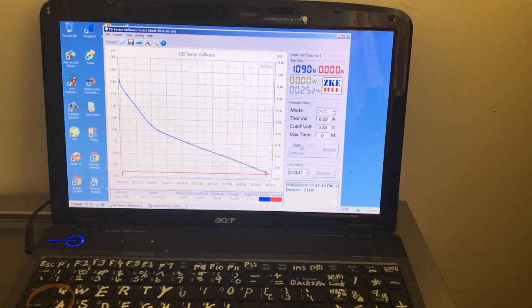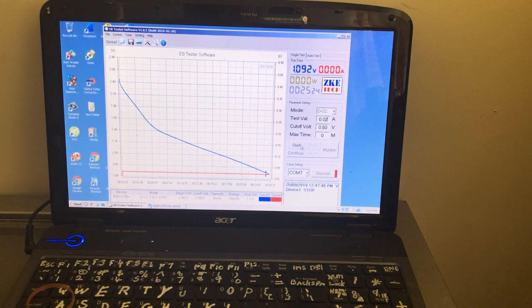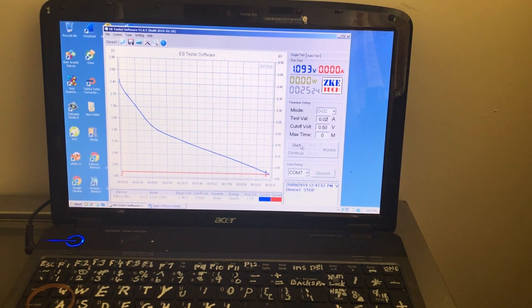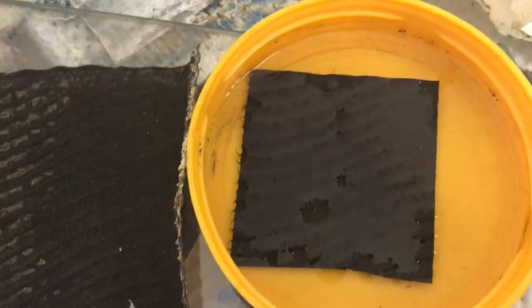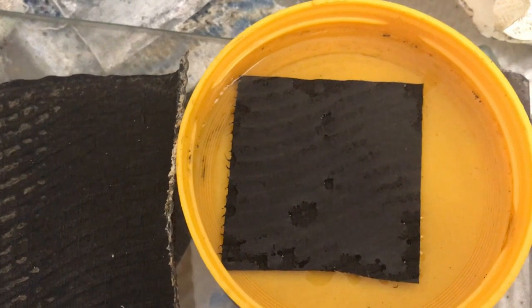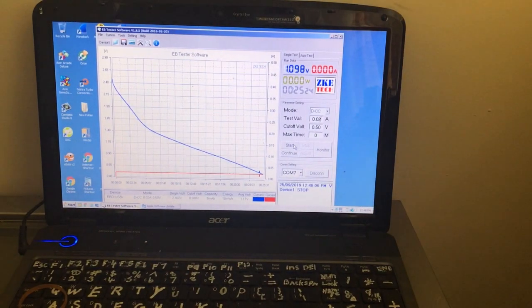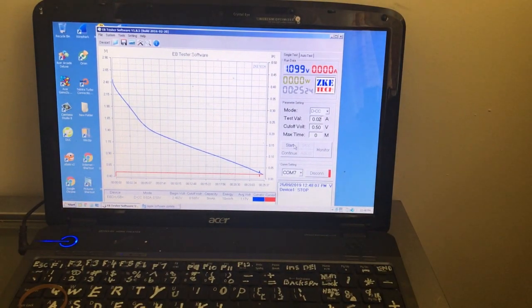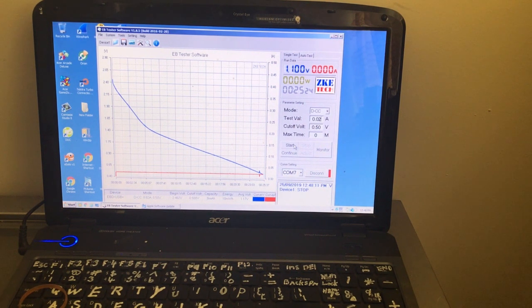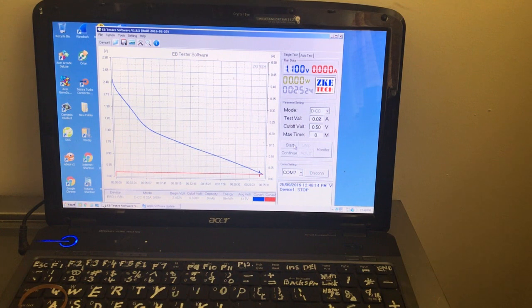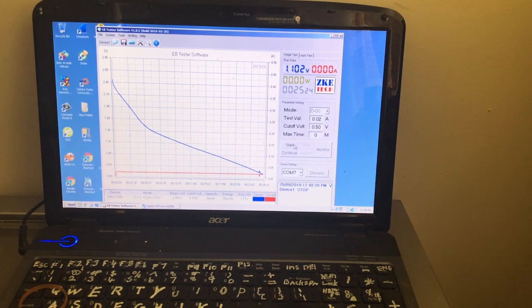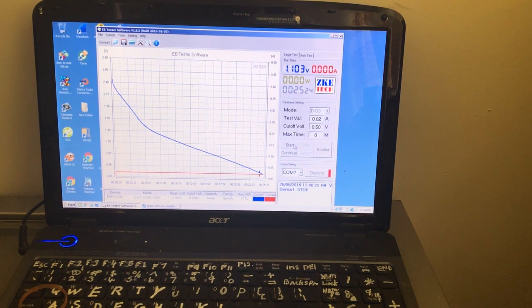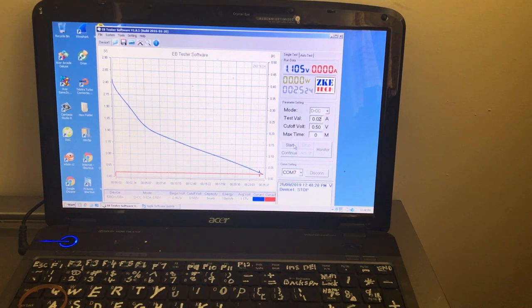Okay, back with the 10 minute charge. It actually almost doubled the cell's performance. 9 milliamp hours and 10 milliwatt hours. So, I'll repeat the experiment later with the extra piece of paper towel. It's got to be in there for about 3 hours. So, I'll put the rest of them in there. And maybe today or tomorrow I'll get back. So, layering actually seems to work. And the carbon coating is actually high in resistance. So, having that lower probably would increase the cell's performance even more. I'll just have to play around with the binder mix.